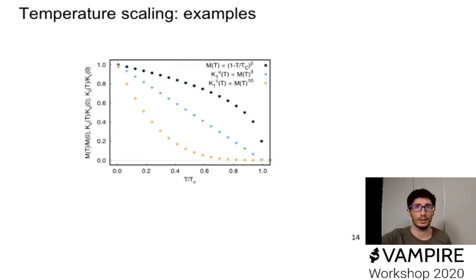And just as an example, here I show the scaling where I have not only the magnetization as before and the uniaxial anisotropy, but also the scaling with temperature of a system which has a cubic anisotropy. Now, this doesn't affect the magnetization because the magnetization temperature dependence, where we're looking at the length of the magnetization, will depend on the exchange and not on the anisotropy.